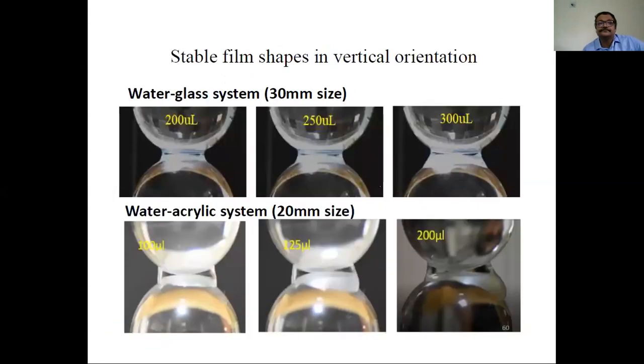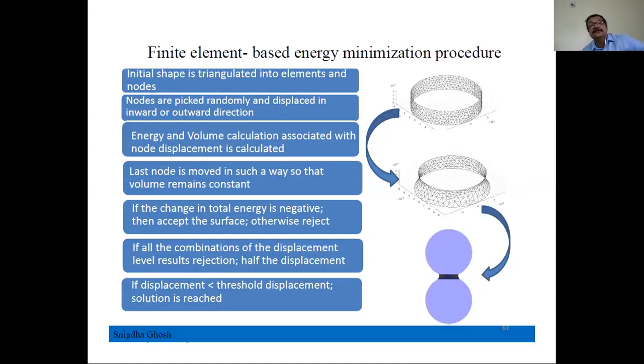So these are some of the experiments. I don't want to go into the details, but you can see 200, 250, 300 microliters, sorry. And you can see that somewhere here it starts coming out. So there are a lot of interesting phenomena. We also did mathematical modeling. Again, this was a tough modeling exercise where you start with the surface, that means the liquid film, and then you do so-called energy minimization. There is an interfacial energy, there is a contact angle, and gravity acting. What we do is randomly change one node, find out the area, change again, and you do this iteratively. So it is computationally very intensive and needs a lot of parallel processing.